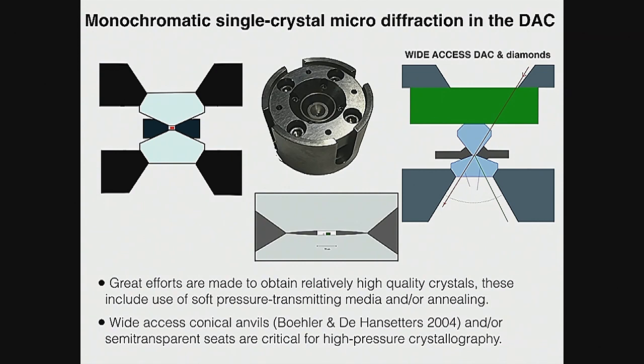So about 10 years ago, I was part of the group that started to do monochromatic single crystal diffraction in diamond anvil cells. So problem one, the windows tend to be small. Luckily, the same scientists that work here that developed that large volume diamond anvil cell also developed these wide opening support diamond anvil cells, so we can start getting enough access. You can also get that by using some semi-transparent materials to support your diamonds as well.